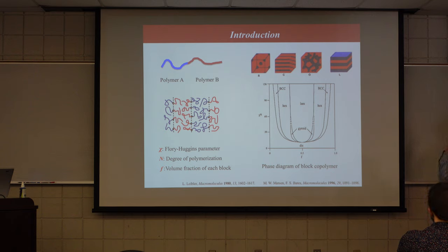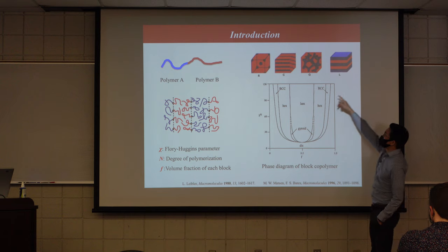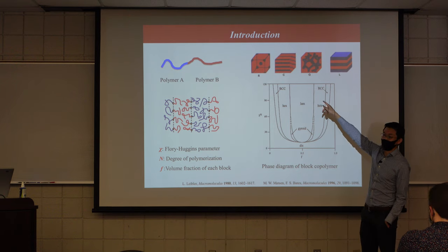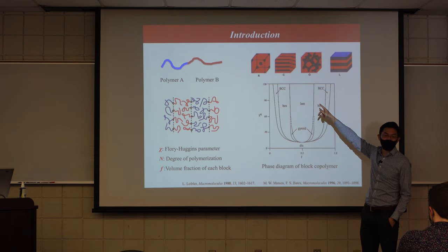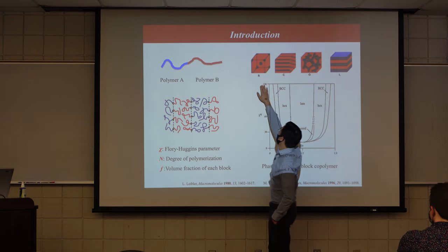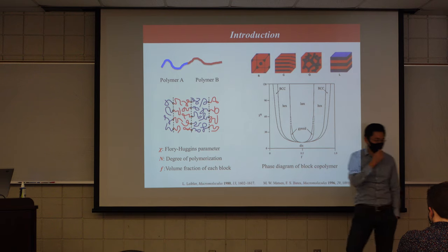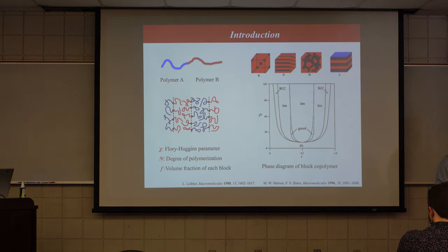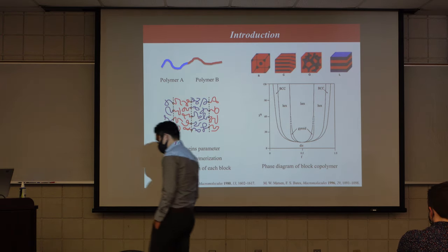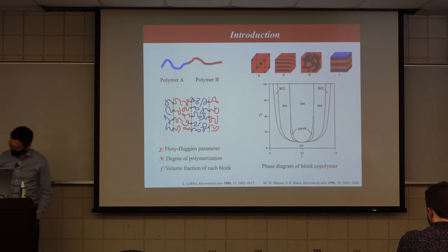So X-ray is perfect because you can look at the structure factor. You're not looking at the shape of each individual domain. We actually cannot easily do that, but you can tell the self-assembly, whether it's spherical or cylindrical, by looking at where the peaks are, especially the higher order peaks. I'll chat about that as well. So in other words, it's a great way to use X-ray scattering slash diffraction in this case. It's more relevant to diffraction, I would say, to quantify the phase behavior.